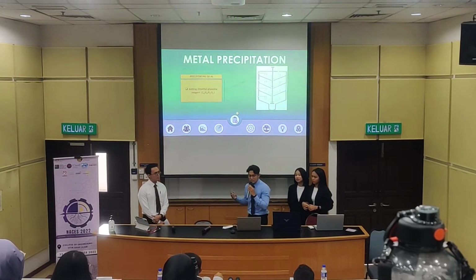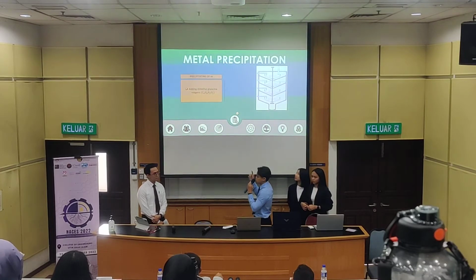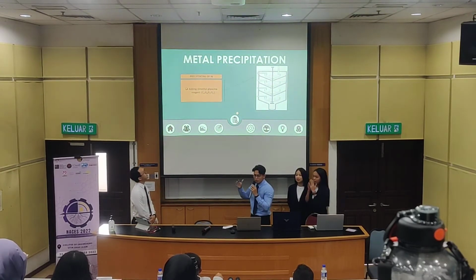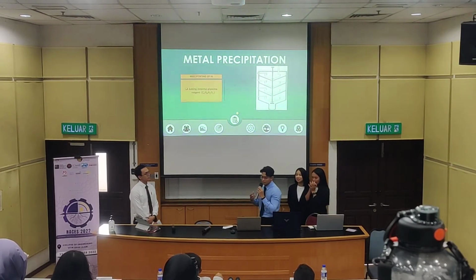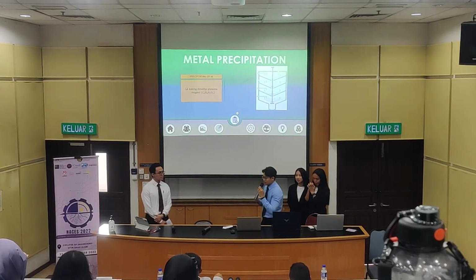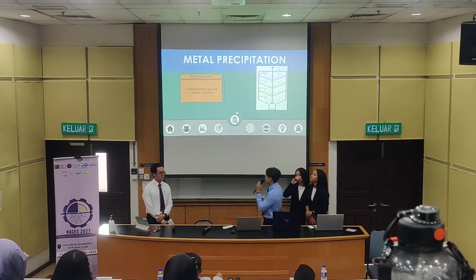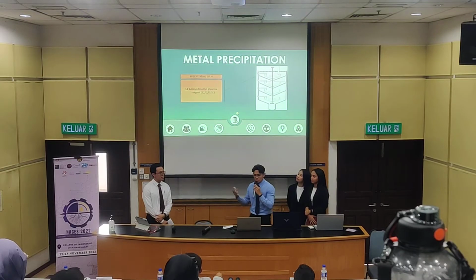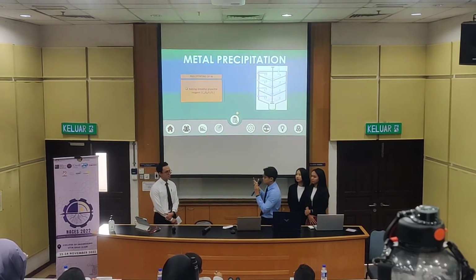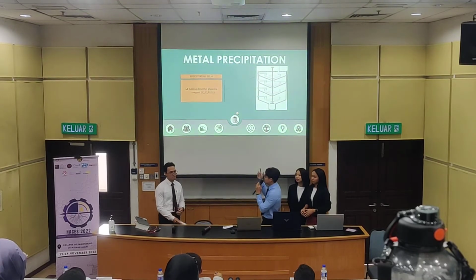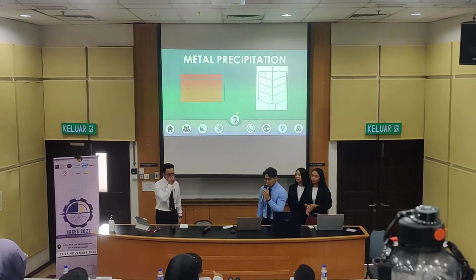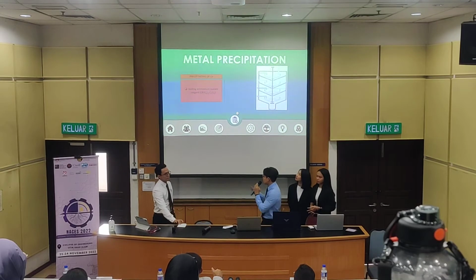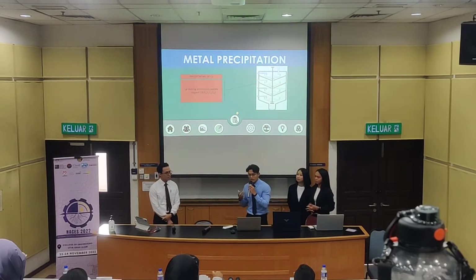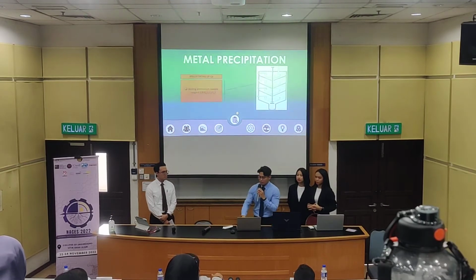So this process started with introducing the leached solution at the inlet, where the precipitation of nickel will take place by adding dimethylglyoxime reagent into the reactor, and then the mixed solution will flow through the solid filter to separate all the nickel precipitate from entering the second stage. So next, at the second stage, precipitation of cobalt will occur by introducing ammonium oxalate reagent into the reactor.